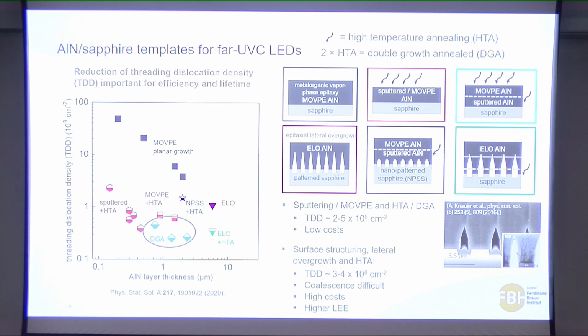And that's basically the values that you see here. So we can get in the 10 to the 8 region and still have reasonable thickness of aluminum nitride. And this is quite a cost-effective method because you don't need any processing. You just need to sputter aluminum nitride and then go with MOVPE. So this helps the cost to remain low.